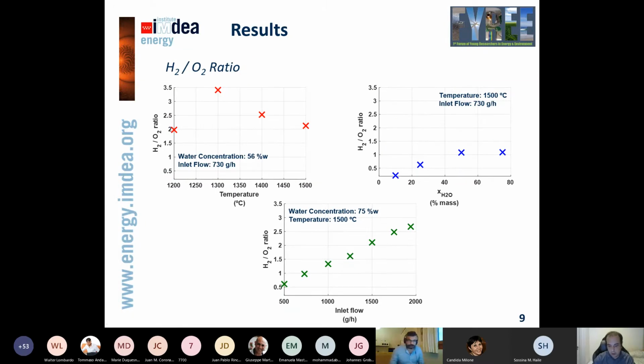If we're assuming that we are at thermodynamic equilibrium, then this ratio should be 2. If we're able to split water, the concentration of hydrogen should always be double the oxygen one. What we think, again, is what Sosine just explained: even if we are close to the thermodynamic equilibrium, we are not at that point. And that is what enables us to continuously produce hydrogen no matter the case.